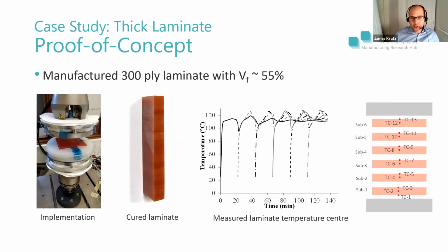Now, if you look at the temperature versus time plot in the center of the graph, you can see how that first sublaminate experiences the cyclic temperature through the process. And as we add sublaminates, they'll have fewer consolidation and temperature cycles, but they tend to have that 15 degree centigrade temperature overshoot. And if our target process temperature is 120, we're actually within about 5 degrees centigrade. So marrying up the traditional manufacturing targets.